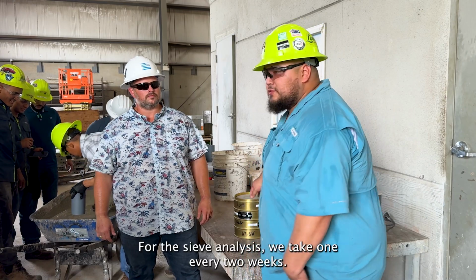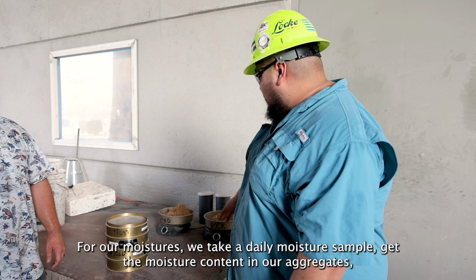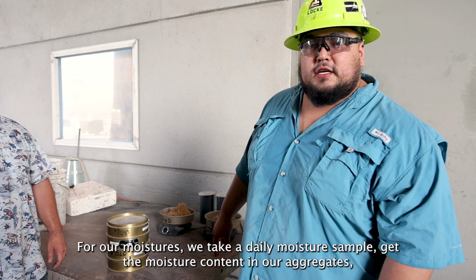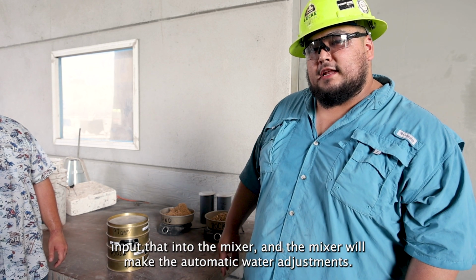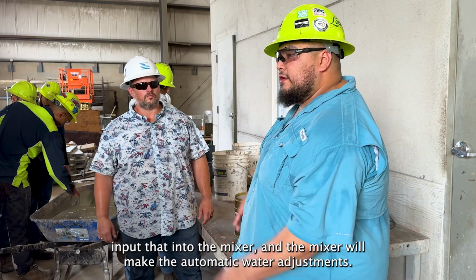To make sure our gravel and sand are in compliance, we take periodic samples of the aggregates. For the sieve analysis, we take one every 2 weeks. For our moistures, we take a daily moisture sample, get the moisture content in our aggregates, input that into the mixer, and the mixer will make the automatic water adjustment.